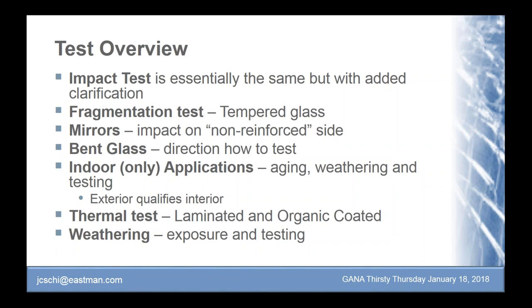They had actually adopted that prior to the ANSI Z97 adoption of the fragmentation test. Mirrors are only impacted on the non-reinforced side, and now bent glass is added to the standard, so it talks about the radius of curvature for the impacting and how to go about that. Again, indoor applications do require some aging and weathering. If you do qualify your product for exterior, it is automatically approved for interior applications. And there is thermal testing, be it in a bake oven or in a boil tank for laminate and organic coated products. And there are weathering requirements, which are either natural exposure in southern Florida or xenon exposure in an accelerated chamber. And those are required today.